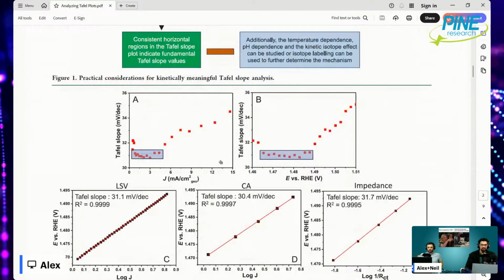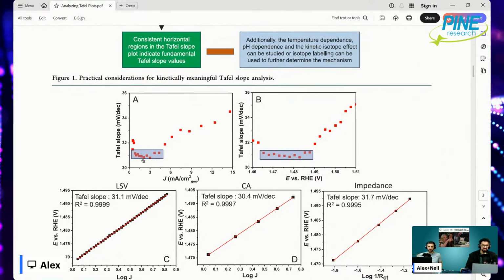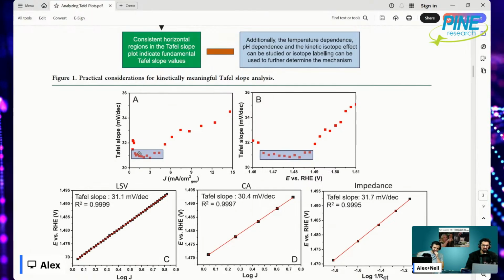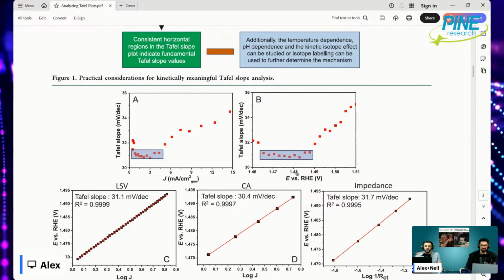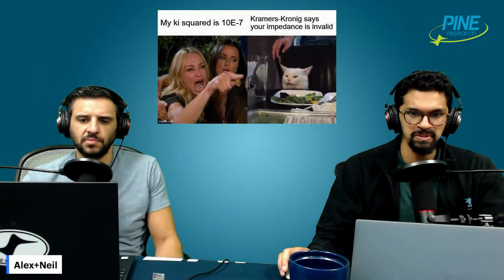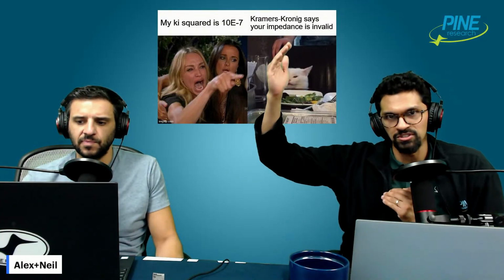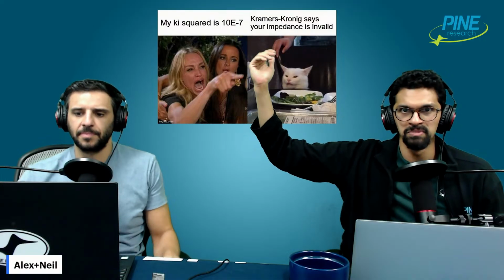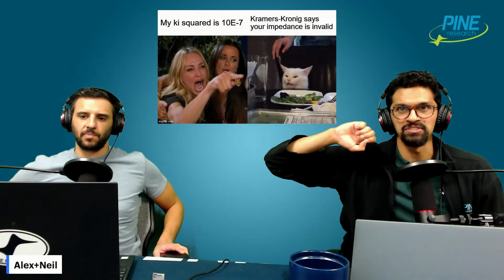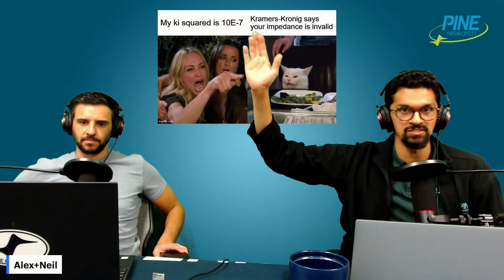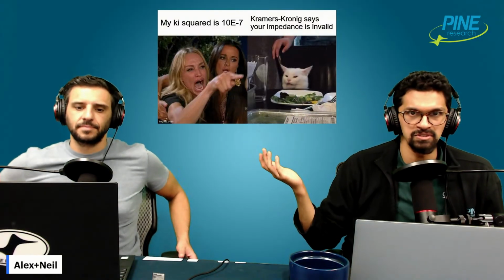And in this case, you can see that the Tafel slope is pretty consistent over this current density, and it's around 31 millivolts per decade, which corresponds to like 4 electrons or whatever. And similarly with this catalyst, they found that it is only within a specific range of voltage that they actually had a Tafel slope that mattered. So the measurement of the Tafel slope between different voltage periods is a good practice, because you might be looking at one slope over this huge range, say 300 millivolts of overpotential, but the Tafel slope itself could be changing across that whole range, and you just picked one that gives you a value that's not very useful.